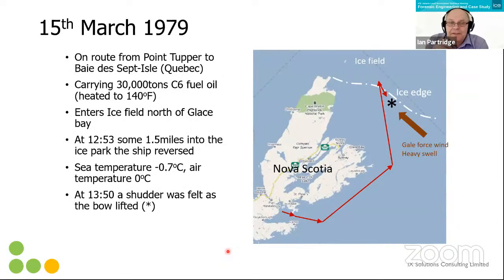So on the 15th of March 1979, in Nova Scotia, the Kurdistan left Port Hawkesbury, went around Nova Scotia and came into the ice field. At the time, it was carrying 30,000 tons of C6 fuel oil at 140 degrees F. We're in an ice field, so it's below freezing. The sea temperature was minus a degree and the air temperature was 0.